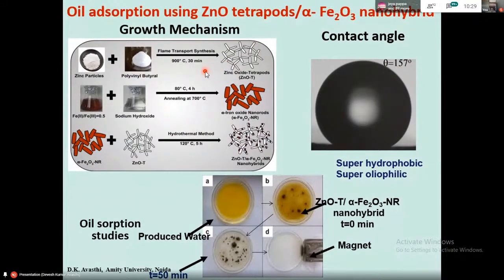And for making iron oxide, we take the iron salt and then sodium hydroxide, and this is the process, and we get alpha iron oxide nanorod kind of things. Now these two things are put together, and by hydrothermal method at 120 degrees centigrade, you see that on the tetrapod this iron oxide gets attached. The nanorods get attached. The zinc oxide tetrapod is quite big in size. It is several microns, maybe 10 or 20 microns. But you can see these 3 or 4 needles coming out. These diameters are about 100 nanometer or so, and on these needles, the iron oxide nanorods get attached.